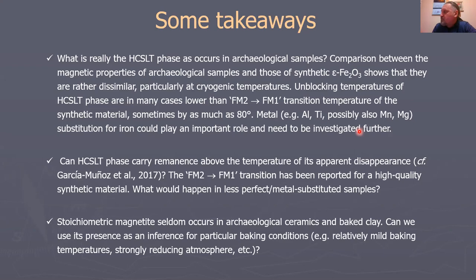In a recent study, a Spanish team that discovered the high temperature phase of epsilon oxide did the same using chromium substitution in the epsilon phase, and the transition temperature expectedly goes down, which we would have hoped for. But the high temperature phase also exists in this substituted epsilon oxide as well, so it's quite a rich field for further study. Yes, with important implications, for sure.